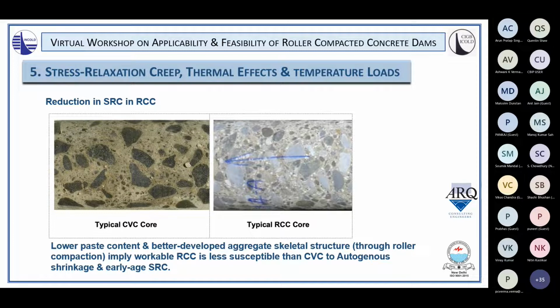And the lower paste content and better developed aggregate skeletal structure that you get in roller compacted concrete through the action of roller compaction implies workable RCC is less susceptible than conventional mass concrete to autogenous shrinkage and early age stress relaxation creep. From one side, because the problem that happens in autogenous shrinkage is in the paste, and because there is less paste in an RCC than is the case with most conventional mass concretes, there is less direct effect of the autogenous shrinkage. And number two, because the skeletal structure is better established through roller compaction, the overall structure of RCC is less susceptible to the stress relaxation creep that would more easily occur in conventional mass concrete.